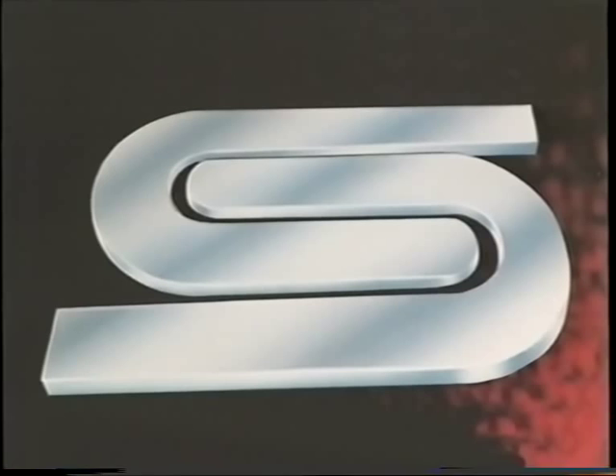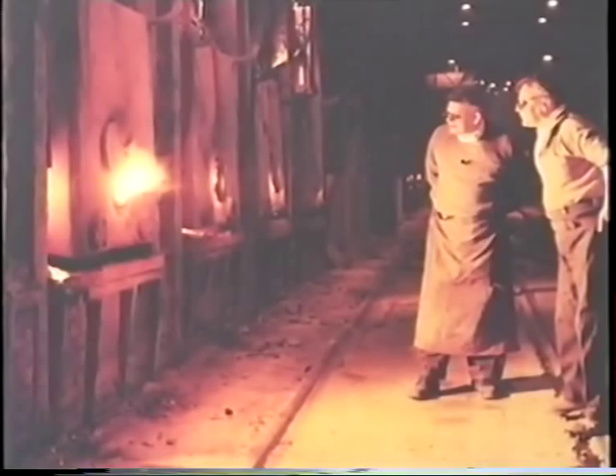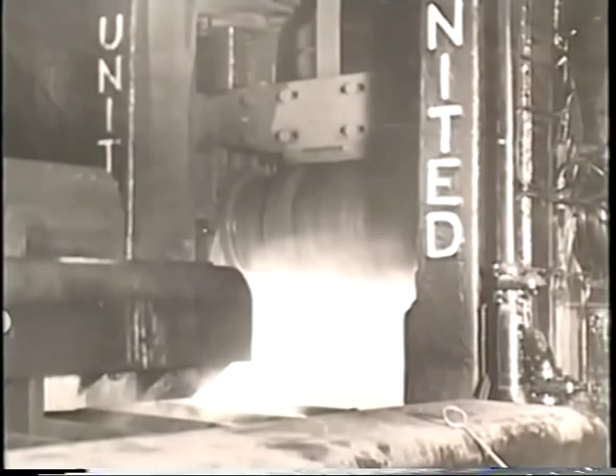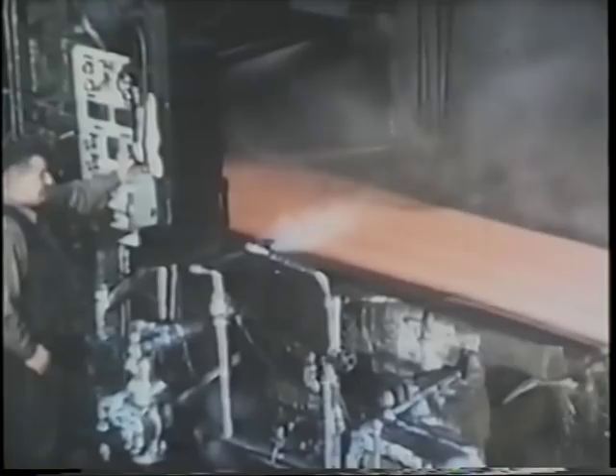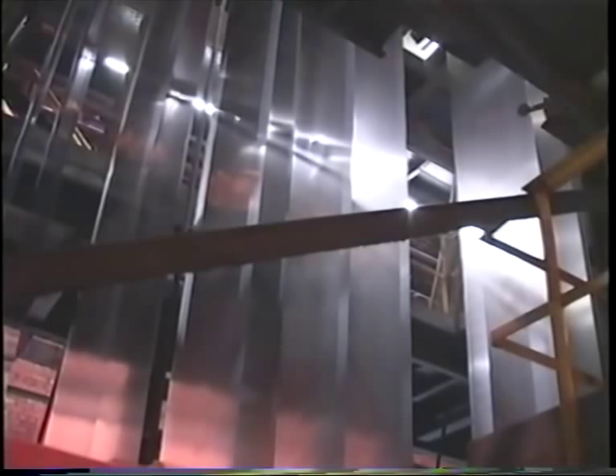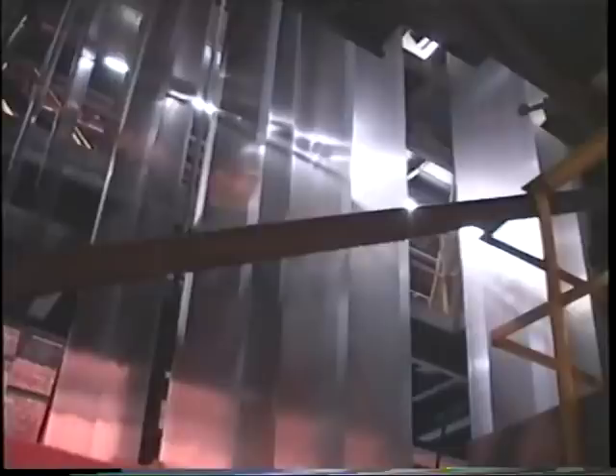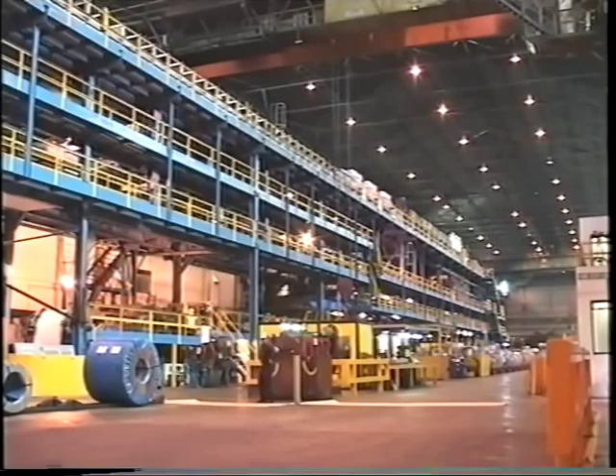Ebbw Vale Works then comprised blast and open hearth furnaces, an LD converter shop for steel making, soaking pits where the ingots were reheated, slabbing mills where they were rolled, hot strip mill for the first reduction into sheets, a cold reduction mill to reduce sheet thickness, 3 electrolytic tinning lines to convert strip into tin plate, plus numbers 1 and 2 galvanizing lines producing zinc-coated strip. It was a huge and integrated operation.